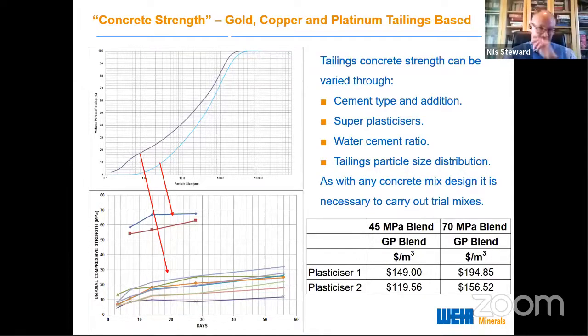Just to give you some idea of price, people will be saying, well, what do these things cost? So we've got typically two strengths here. This is in Australian dollars, so you can put that into your mind: Australian cement prices, Australian plasticizer prices. But typically we're looking at a 45 MPa blend of anywhere from $120 to $150 a cubic meter, and a 70 MPa blend from $160 to $195 a cubic meter.